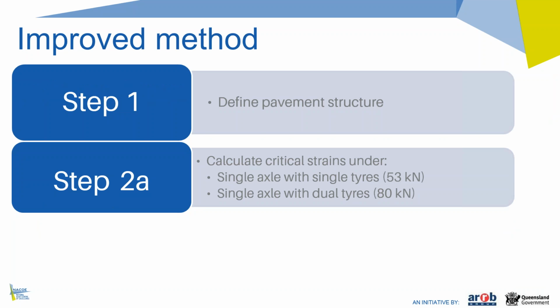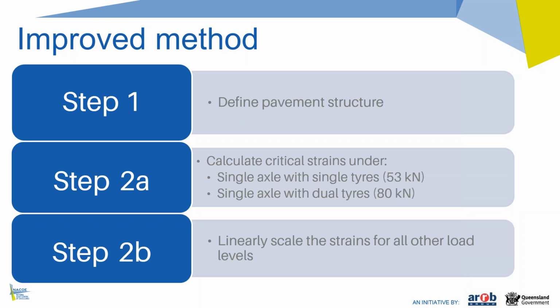So this now leads me to briefly describing the new method. The method's fully detailed in the technical note, and there's also a worked example in the technical note for a full depth asphalt pavement. The first step is quite simply defining the pavement structure, including the material inputs to be used, so that's no different to what we currently do. The second step is in two parts, and this is the method for determining the strains under each individual axle in the traffic load distribution. Firstly, the designer calculates the critical strains in the asphalt under both a single axle with single tyres and a single axle with dual tyres. This still only requires one CIRCLY run, except now with two load types rather than one. And the tech note defines the axle loads, tyre spacings and contact stresses to use.